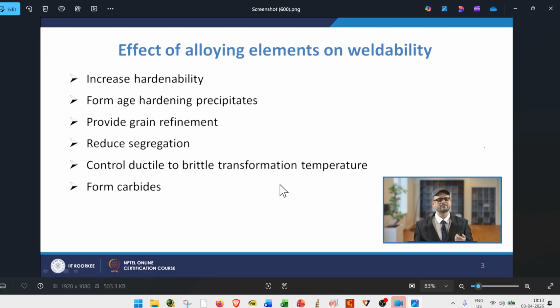Next, age hardening precipitation. Some particles may form due to age hardening, because we are heating to a certain temperature and holding it for a certain duration of time. So aging may take place and some precipitations may form. Then, providing grain refinement: some elements can promote grain refinement. It also reduces segregation, so some segregation of the elements can be reduced. And it controls the ductile to brittle transition temperature. Just like iron, if we go below 0 degrees and so on, it transforms from a ductile material to a brittle material. Those things we have to control.